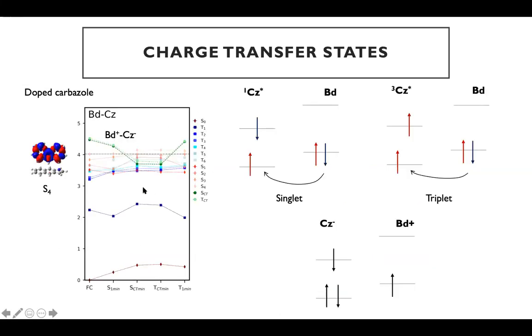Just to go a little bit more into detail on what could happen here. You will have the molecule that is initially excited, the molecule of carbazole. If you calculate the energy levels of the impurity here, you will see that it is going to be a little bit higher in energy. So you expect that the electron transfer is going to happen in this direction. In that case, what you will get in the end is a charge transfer state where you have carbazole with an extra electron, and the impurity with a plus sign, I mean, with a hole in the system.